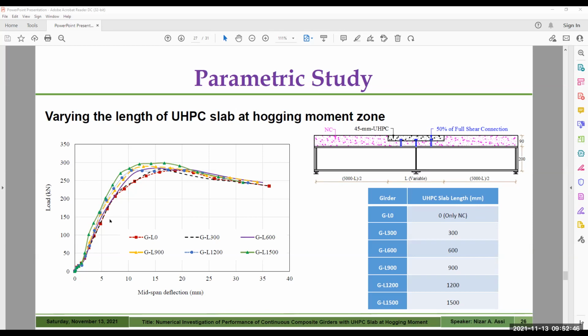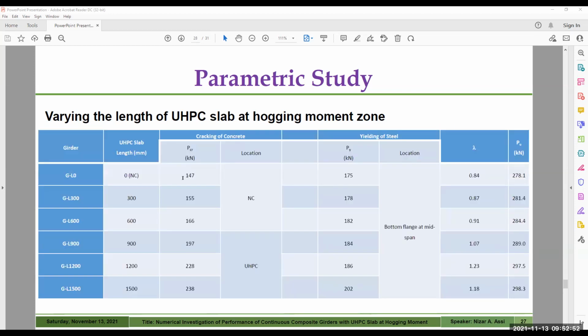In terms of cracking load and yielding load, as increasing the length, the cracking load will increase as well. As the length of the UHPC slab increases, the cracking load and the yielding load increase. But for the small length, from 0 up to 600mm UHPC length, as you see, the cracks developed within the normal concrete, not within the UHPC. But with a length higher than 900mm, the cracks developed within the UHPC slab, and the cracking load